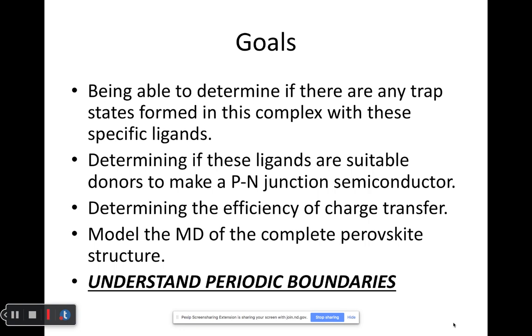If you have an image of an orbital, how would you discriminate between trap and no trap? What's the difference in the shape of orbital? Well, I guess the trap state in the dots. No, not DOS. Plot of orbital partial charge density in space. How would a trap state look like? Just the orbitals plotted? Yes, they look like clouds, but where these clouds are localized is different for the normal intrinsic state of perovskite and for a trap. They'd be localized on the surface?